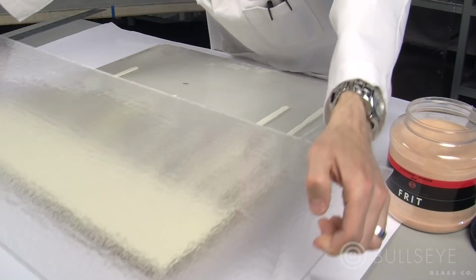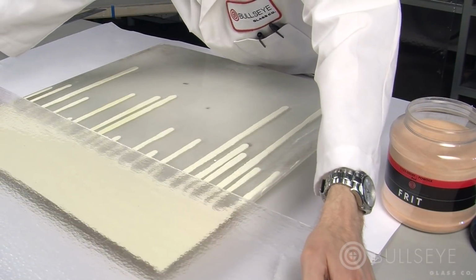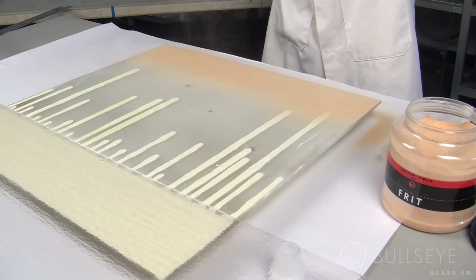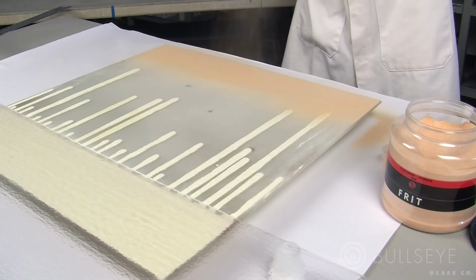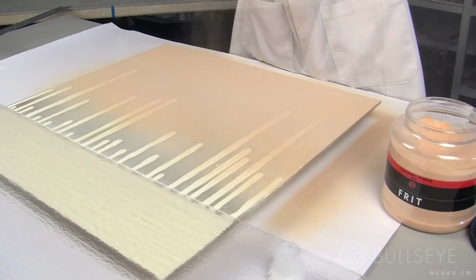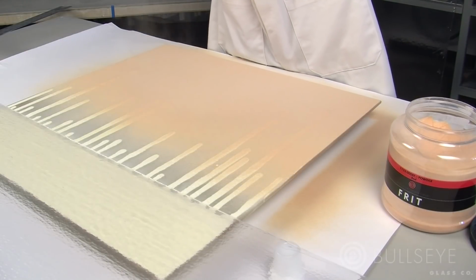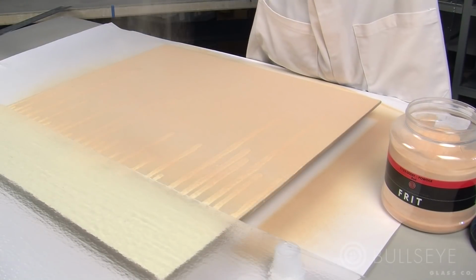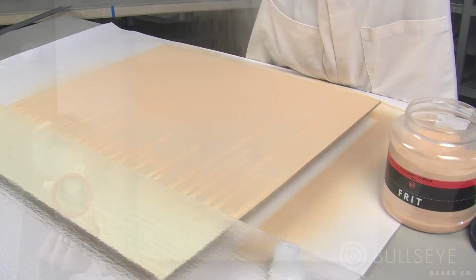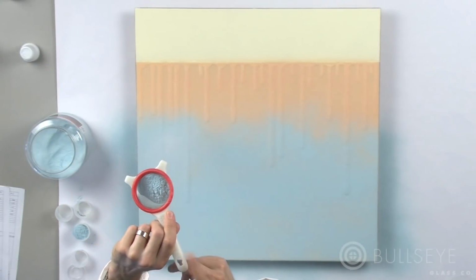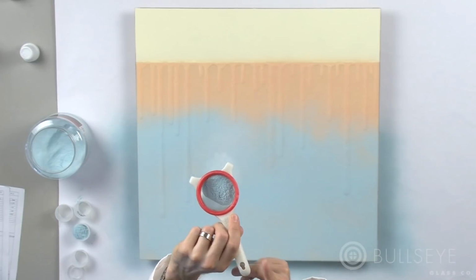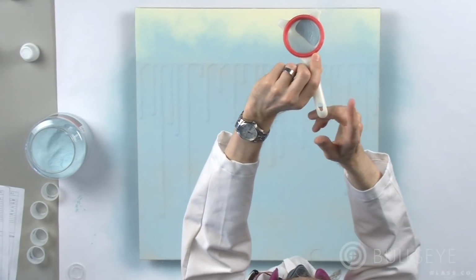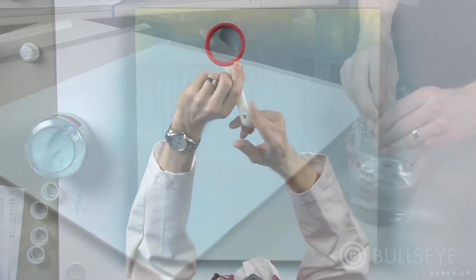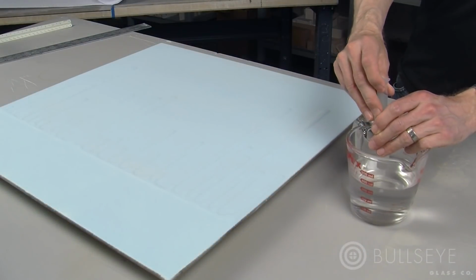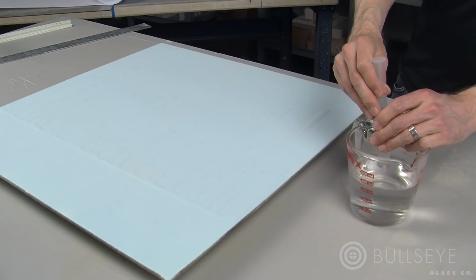And then I use that same piece of glass to mask that upper area, and I lay down 12 cups of the 1122-08 red powder in the lower area, completely covering up those drips, which will actually be there physically. You can see their shadow and relief. And then I come in and I cover all of that with 5 cups of 0146 steel blue powder. Then I reclaim a cup of that.